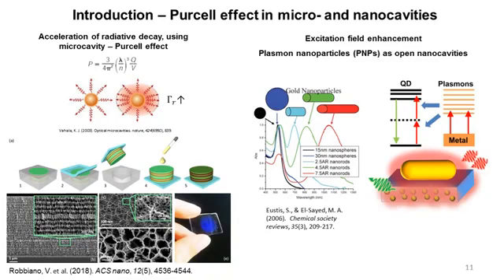The second way to increase the photoluminescence signal of quantum dots under two-photon excitation is to enhance the local field near metal plasmonic nanoparticles. Indeed, plasmonic nanoparticles can serve as open nanocavities, that can concentrate the electromagnetic field on the nanometer scale. This makes it possible to significantly increase the local intensity of the excitation field and thus significantly increase the probability of absorption for quantum dots located nearby. In this presentation, I'll discuss both ways.